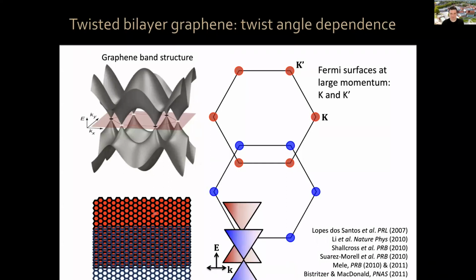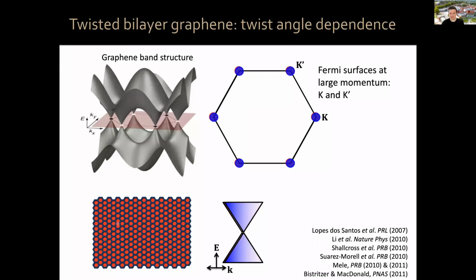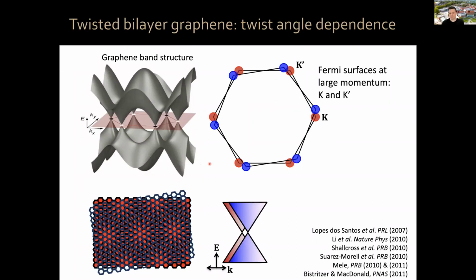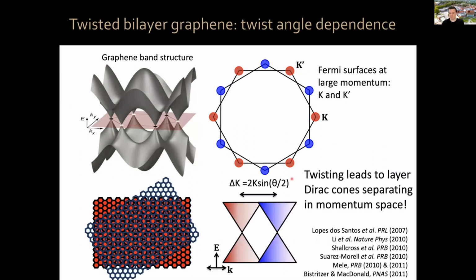In real space, the lattices would be a line if you just put it exactly on top. And in momentum space, the reciprocal spaces are also a line. Now, if you rotate these two lattices in real space, the reciprocal spaces also rotate. In particular, that leads to a separation of the Dirac cones in momentum space. This separation in momentum space between the charge neutrality points of the Dirac cone of layer 1 and the Dirac cone of layer 2 is proportional to the sine of half the rotation angle.